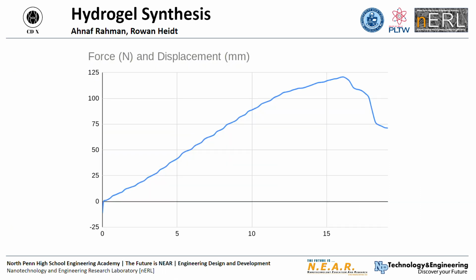This was relatively okay because we were still able to get data, and for the force displacement graph, we got a force of around 120 newtons over a distance of 15 millimeters. And for the stress strain graph, we got around 0.9 megapascals of resistance over the same distance.